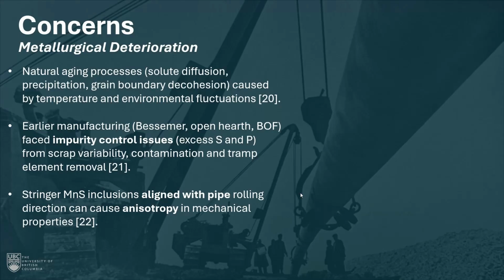And as I mentioned just now, high sulfur content can result in manganese sulfide inclusion. These are essentially more ductile compared to the base steel. So during pipe rolling, these sulfide inclusions can align themselves with the rolling direction. And then this can cause anisotropy in mechanical properties like tensile strength, ductility, and fracture toughness.